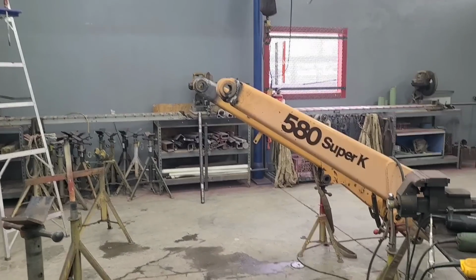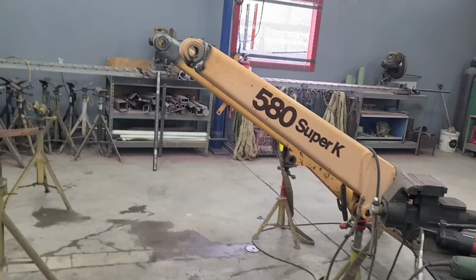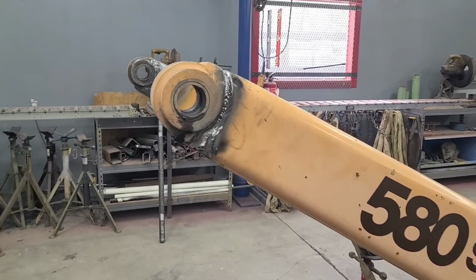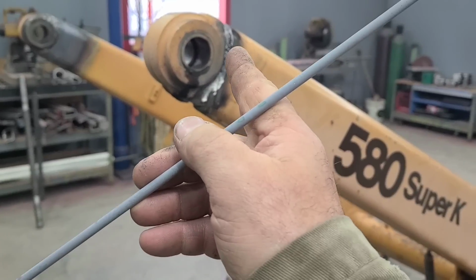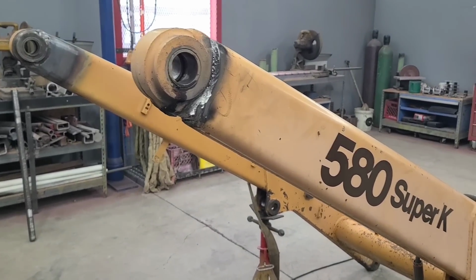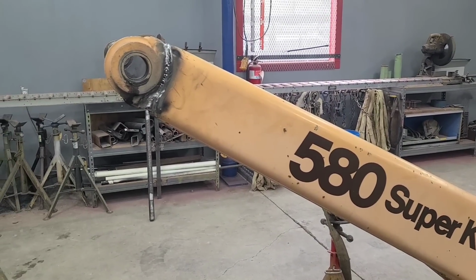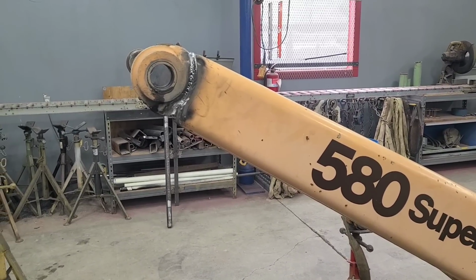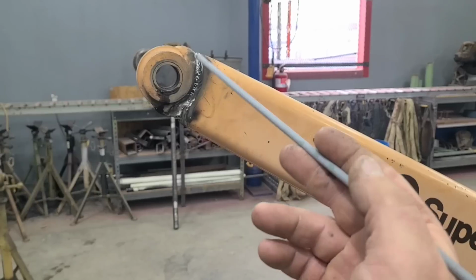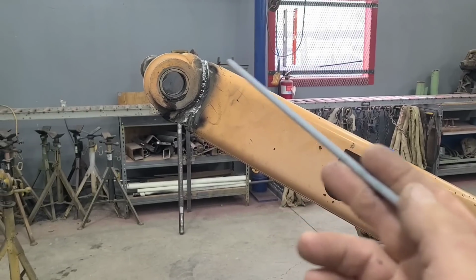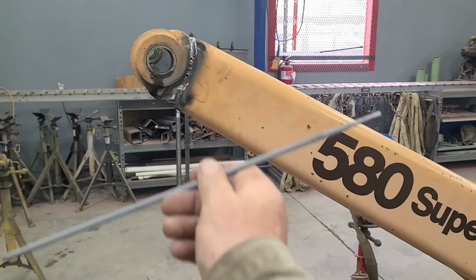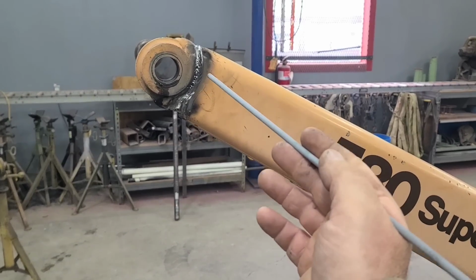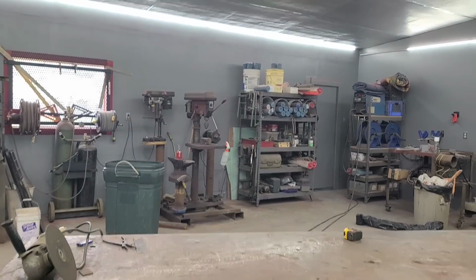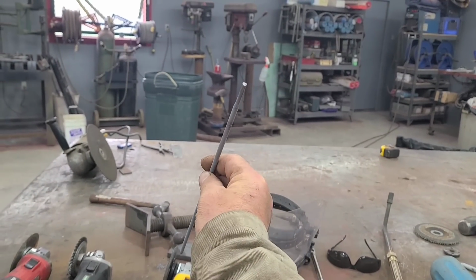So I ran a pass around this with my 5/32 5P plus pipe rod. And I use this rod because deep into the penetration, deep into this weld, I want to have a lot of control with a lot of heat. If I was doing this with a 7018, I would not be able to have a lot of heat and a tremendous amount of control like I do with this rod. So what I'm talking about here is I was running that machine on 165 amps with a good size rod. This is a 5/32 rod. I have a lot of metal here.